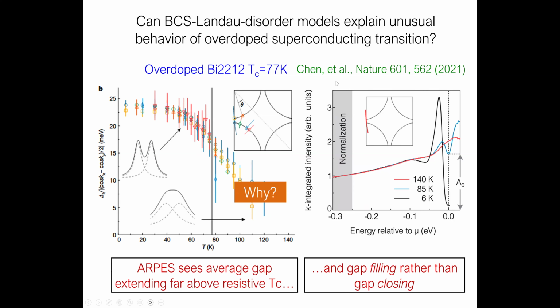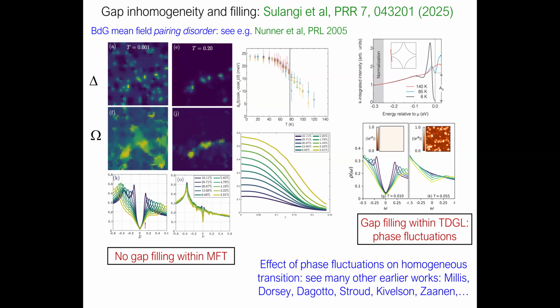Okay, so these are data from this paper, I think from the Stanford group, for a 77 Kelvin sample. And the other thing is that whereas you would expect from a BCS type model that when the temperature gets close to the transition, the gap closes, instead, what's seen in angle resolved photoemission, and this has been seen for a long time, is that it fills. The density of states at zero energy rises, and eventually it looks like a normal state spectrum. So the question is, can you explain this with this mean field theory that I have been discussing? Well, the answer is partially.